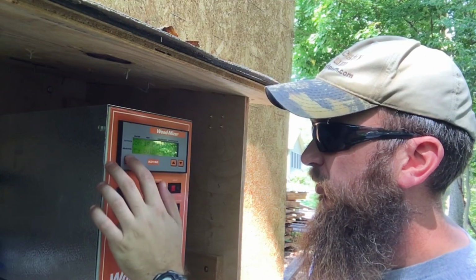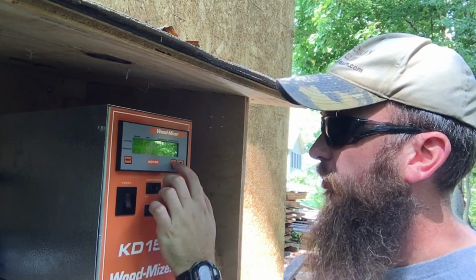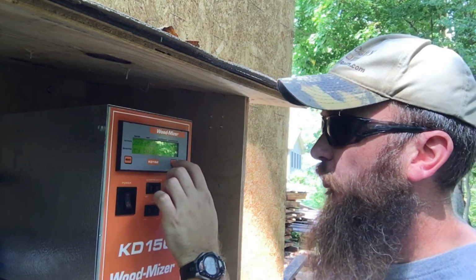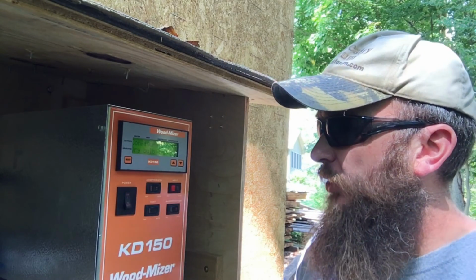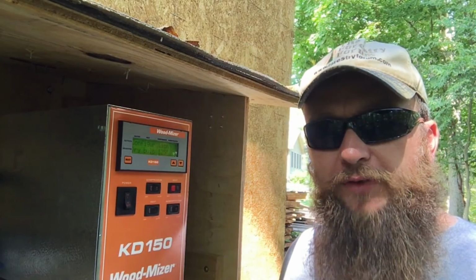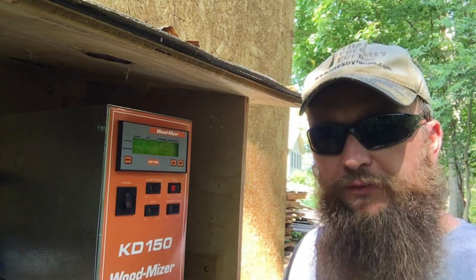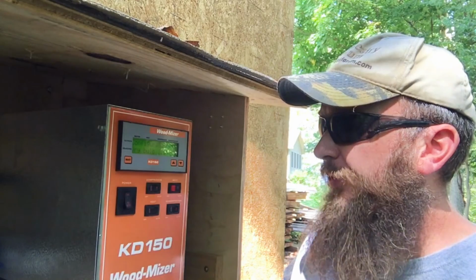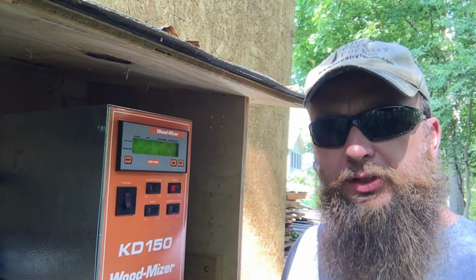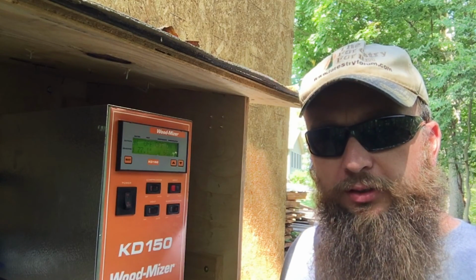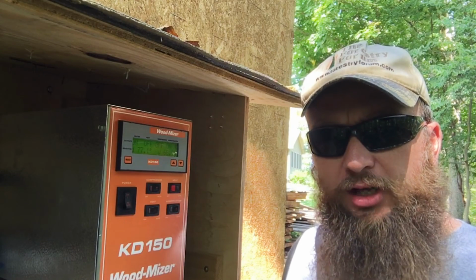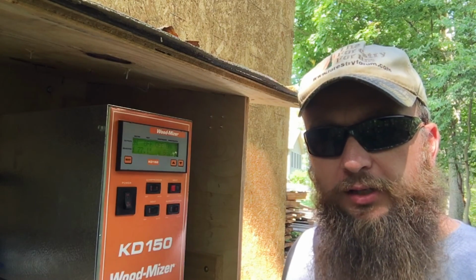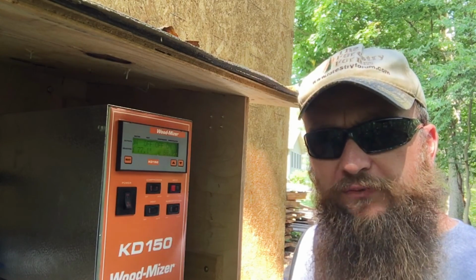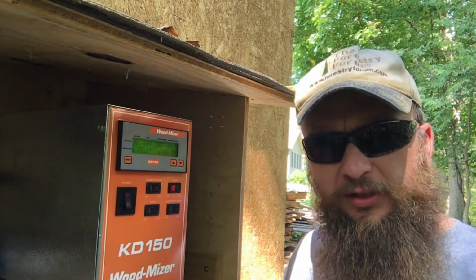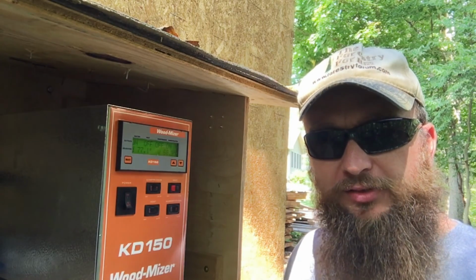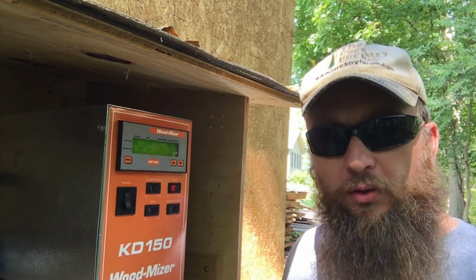Configuration. We're going to set the dry bulb for 125 degrees. So theoretically, when it reaches 125 degrees, it's going to try to hold itself at 125. But one thing this kiln will do that I've been told is it will get warmer than you want it to. You have no problem heating these things up. The only problem is they get too hot. So once it gets to 125, we're going to monitor this thing extremely closely and probably open up the vents a little, and some guys even crack their doors.